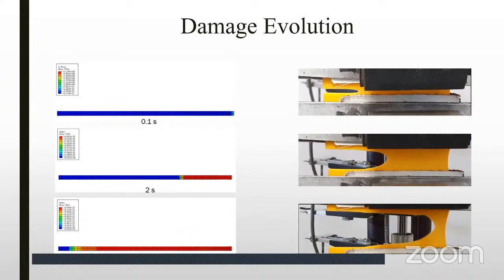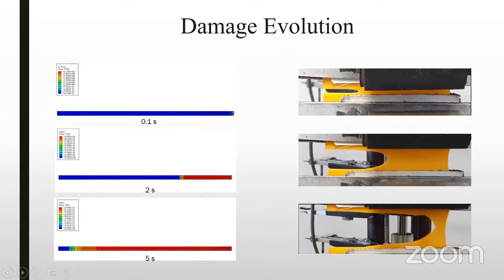Here we can see the experimental and numerical results of the damage evolution. The left pictures show the damage evolution in the Abaqus model in three different time increments, and the right pictures show the damage evolution in experimental tests. You can see the good agreement between the numerical and experimental results.